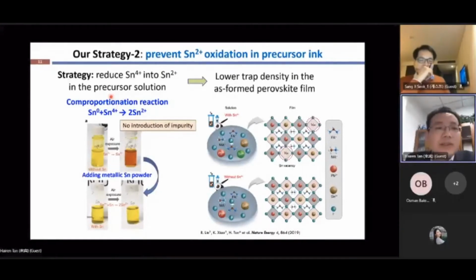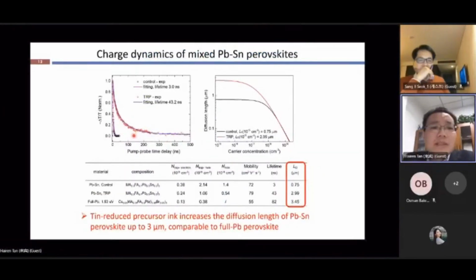So what we do is we add tin powder in the precursor solution, because the tin powder can reduce the tin 4+ states back to the 2+ states. That is what we need for perovskite materials. The benefit of this strategy is that we can much increase the charge carrier lifetime, and also we can slightly increase the mobility of the material.